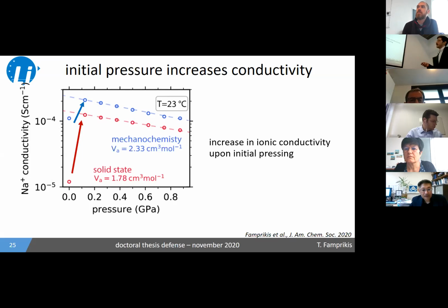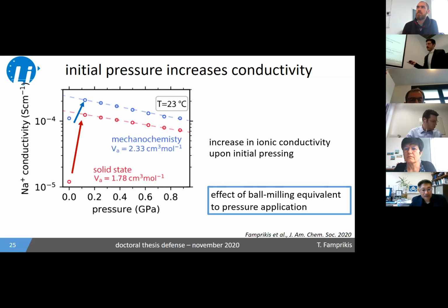which in the case of the solid state sample is most pronounced, and it actually amounts to about an order of magnitude, which is somehow the same effect that has been previously ascribed to ball milling. So in other words, the effect of ball milling to increase the ionic conductivity of Na3PS4 is somehow equivalent to applying a minute amount of pressure to Na3PS4 and measuring in situ.